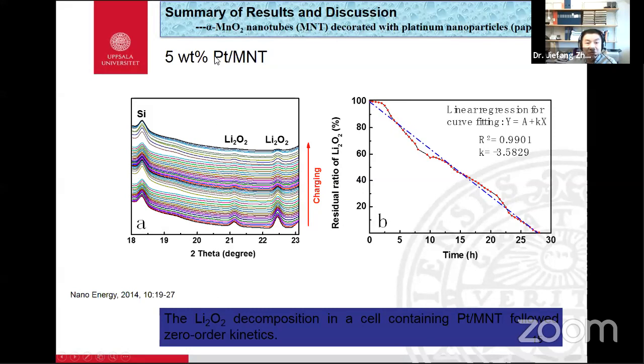from our published work, for nano-sized platinum highly dispersed on alpha-manganese oxide nanotubes. You can see during the charging process, the lithium peroxide peak intensity decreases. We also put silicon inside as a reference. So you can see this is the real decomposition curve. This is the theoretical curve at constant current density.